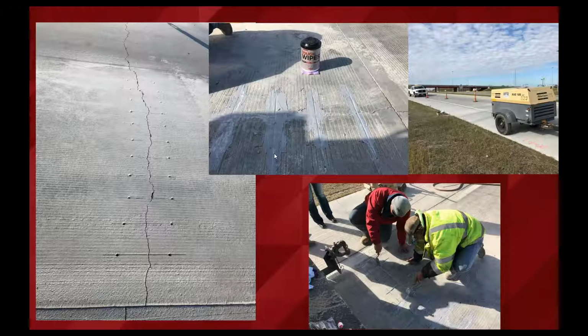This is the picture I was talking about where the crack locks were stacked. So this was an on-ramp to a major interstate, and the engineers at the State Department figured that they should put 3 crack locks per location. So in each one of those prep sites that you see there, there's actually 3 crack locks installed. I believe at a 5-inch depth, 3-inch depth, and then a 1-inch depth is what those were set at. And that was calculated out to be adequate for the stresses that would be exerted on that slab.